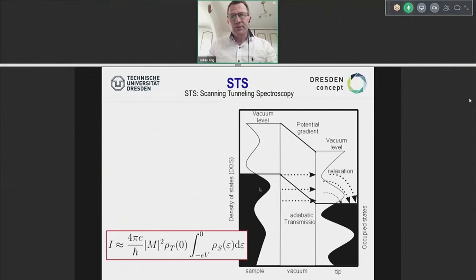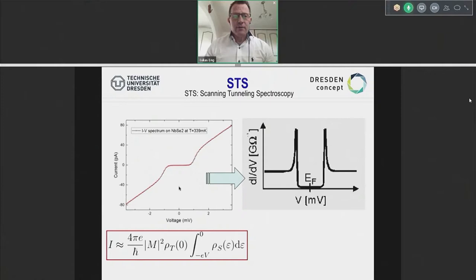Now we can do that basically with any system, even if it's insulating, simply because then we're going to have a band gap or semiconductors. So that means it is possible to take an IV curve. Like in a macroscopic measurement, what you do is you fix your tip above your sample, not scanning, but really fixed at a certain distance. And then you sweep the voltage, which is the x-axis, while recording the current.